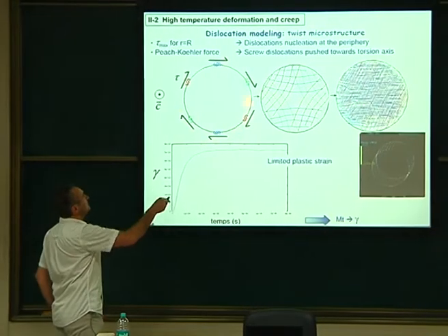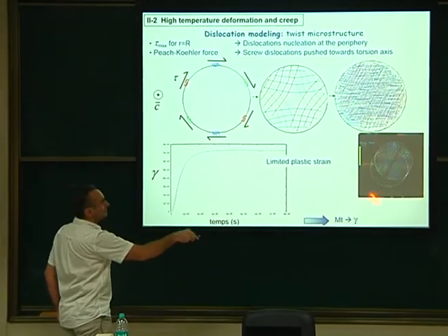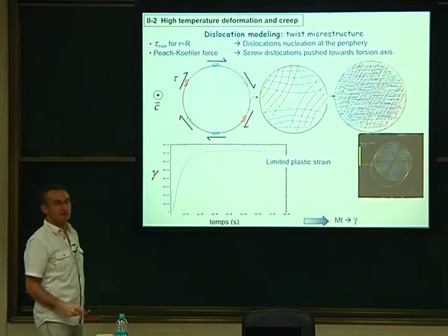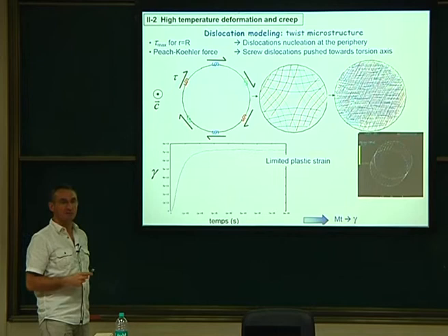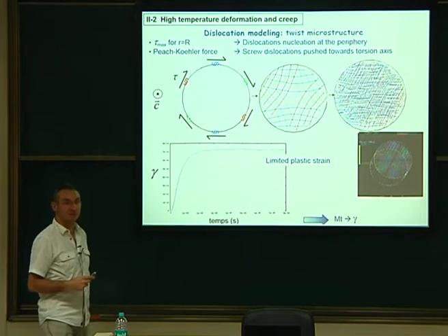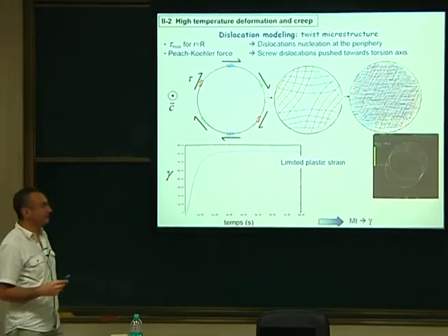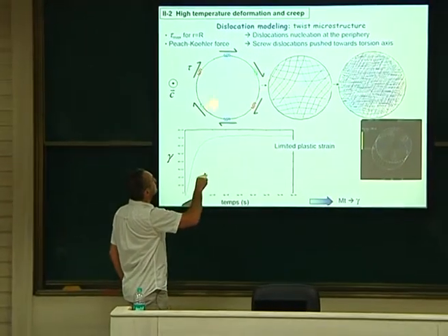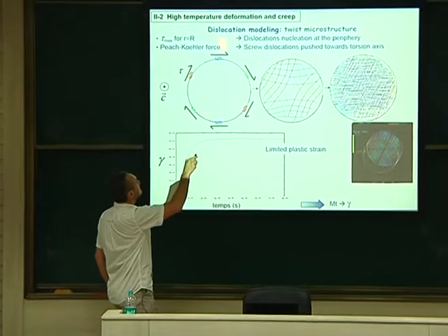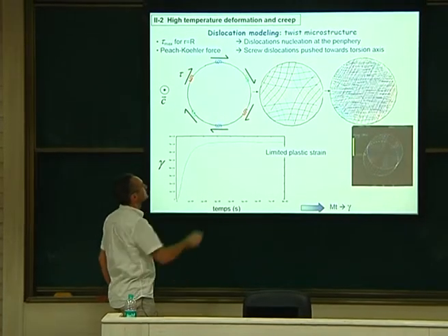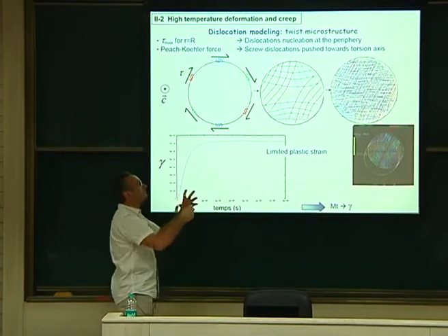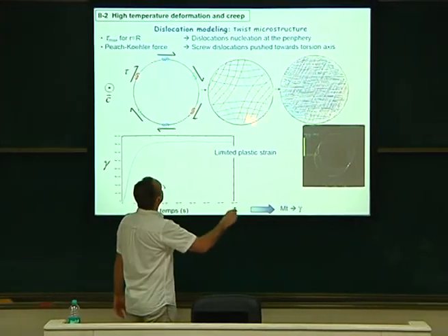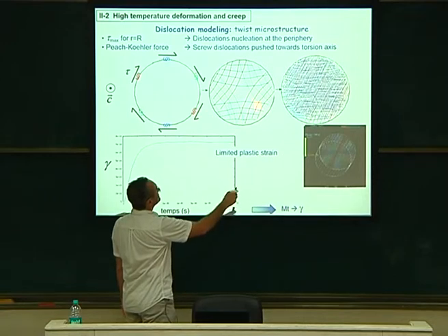You have your circle. This is your domain. You can see it here, the white cylinder. In this domain, you will put some screw dislocations, because screw dislocations are the only ones that could accommodate rotation, a twist. A twist is made of screw lines. You can see that here are all my sources. So I put S like source. These are the same family source, same family source, same family source. And when you apply your torque, your momentum to the specimen, they emit dislocations toward the center like that.